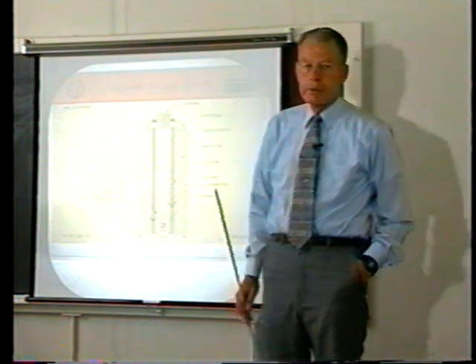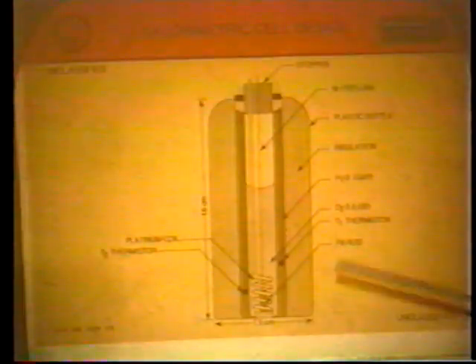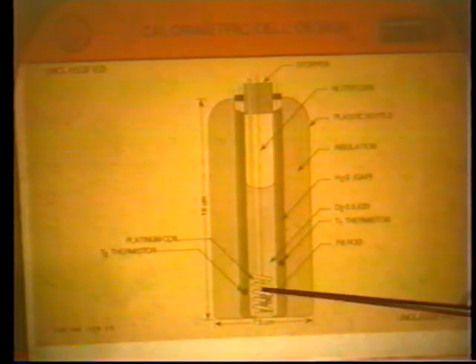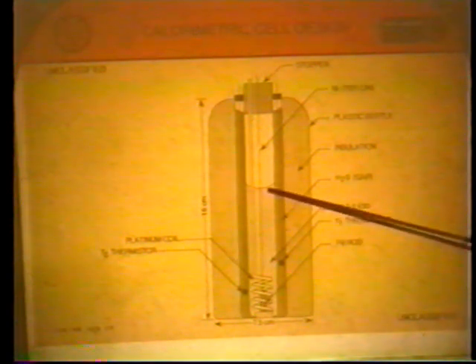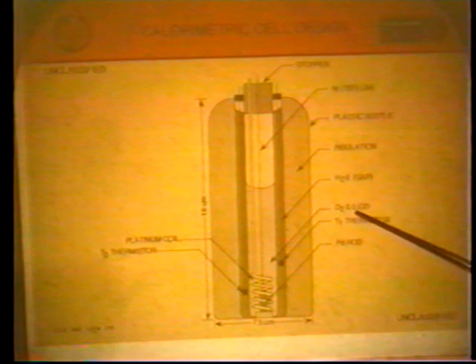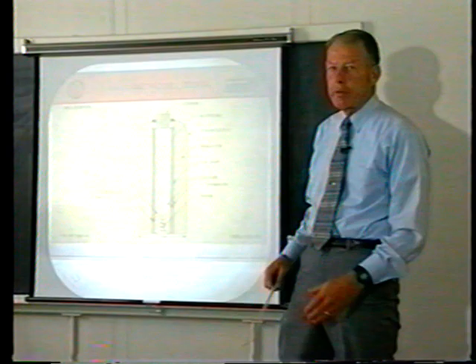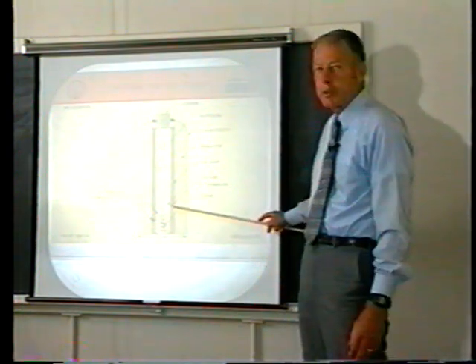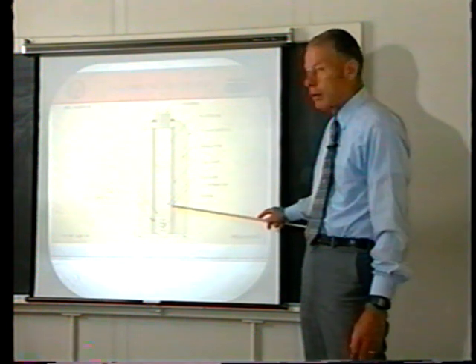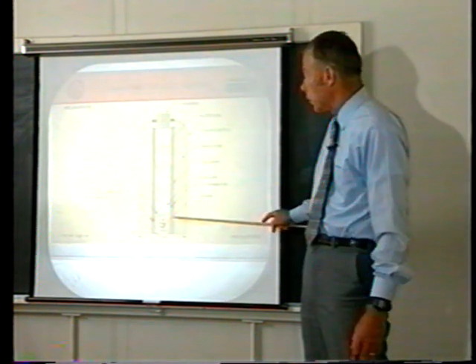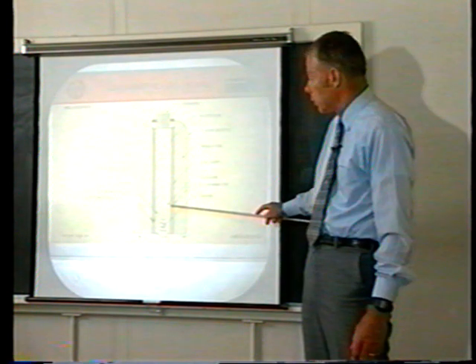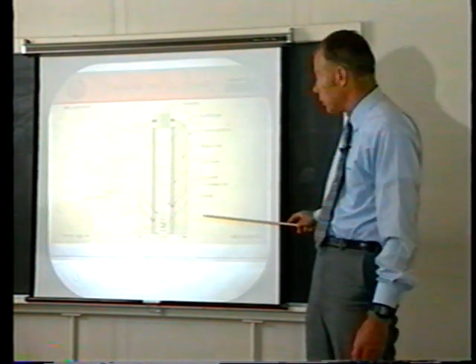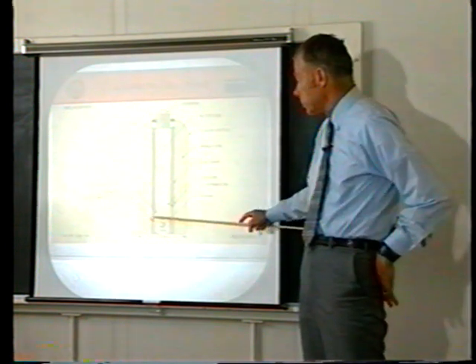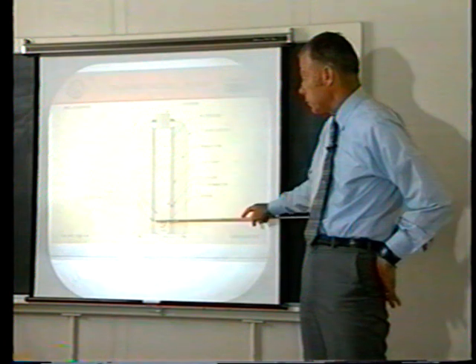This view graph shows the design of our calorimeter. This is a palladium rod that we used in the center. This is surrounded by a platinum counter-electrode or anode. The cell was filled with heavy water containing LiOD, and we measured the temperature of our cell by 2 thermistors. This differed from most other designs in that we placed our thermistors on the outside surface of the cell in a gap filled with distilled water. And so we measured the temperature difference between the wall of the cell and the water bath out here. The thermistors were placed at opposite sides of the cell at 2 different elevations or levels.